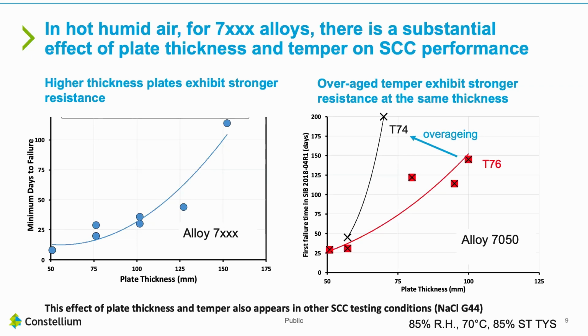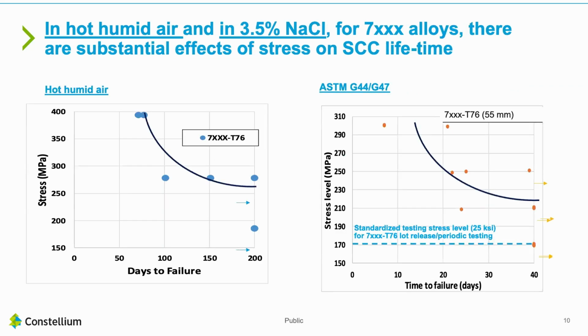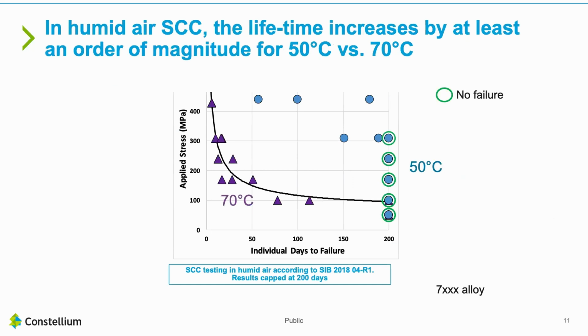This is also observed in a standard chloride test. And when you change the stress, you also change the resistance. The higher the stress, the lower the stress corrosion resistance in both tests. Temperature is also an important factor. When we test at 70 degrees, the test is more severe than at 50 degrees, but even 50 degrees, compared to the tank application that spends a long part of its life at cryogenic temperature, remains a severe test.